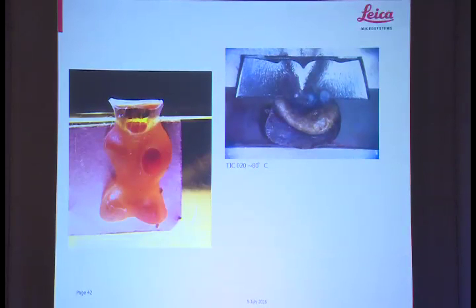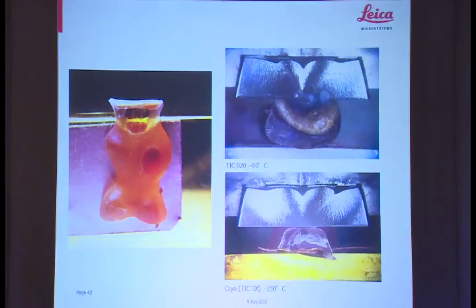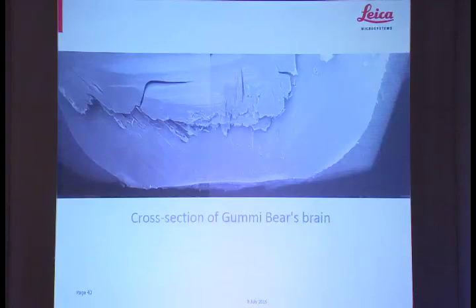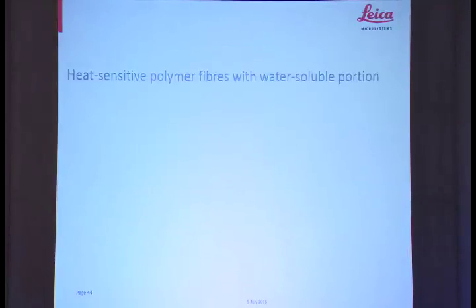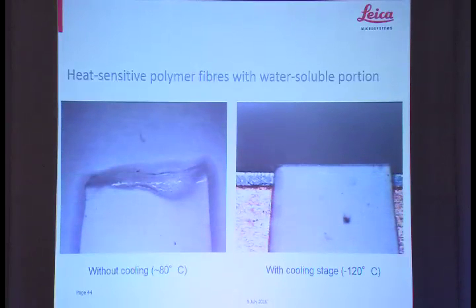So we developed from this a cryo stage. We held him at minus 150 degrees centigrade and successfully cut through the head and produced this very large area of flat surface. So this was the first step for us to identify that, yes, we can use this process, because a customer had asked us to prepare a sample of a water-soluble polymer. And same thing again, room temperature, it failed. Using cryo, we managed to maintain a beautiful structure.